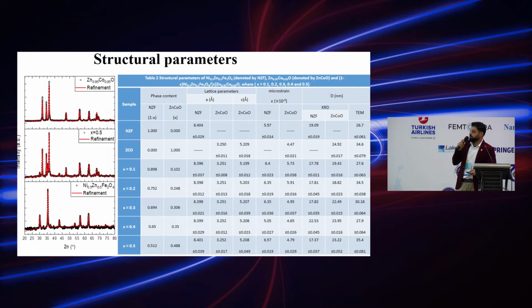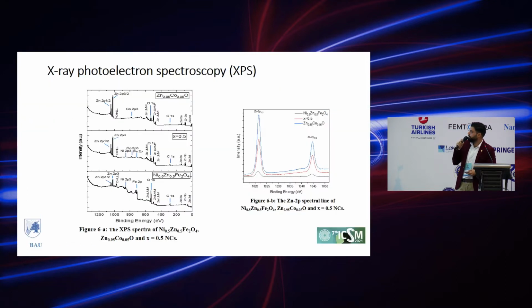Rietveld refinement was employed for all XRD patterns, and the phase content was determined and was found matching the theoretical phase content. The lattice parameters were found fluctuating around values previously reported in the literature. These fluctuations were assigned to the microstrain induced on the lattice due to the addition of the zinc cobalt oxide. The grain size and the crystallite size obtained from XRD and TEM were also found comparable.